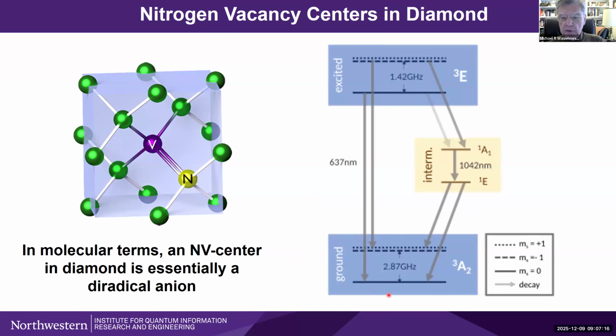And so that triplet ground state can be photoexcited, but the magic, if you will, for NV centers happens in the follow-up intersystem crossing event. In other words, there's a spin-selective intersystem crossing to a singlet state, a so-called shelving state, which directs population from this excited triplet state into this state, and then back to the ground state. So this selectivity results, if you continually pump the system, in polarizing the ground state T0 level of the triplet.